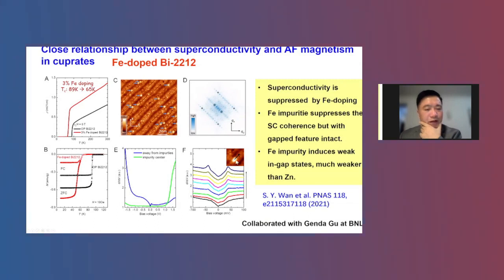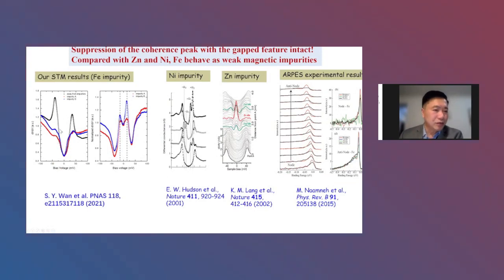But far away, you can see that it becomes a normal superconducting curve. Okay, so this is on the iron impurity doped BSCCO 2212. And here shows the contrast for the tunneling spectrum measured far away from the iron impurity, which shows a typical d-wave superconducting tunneling spectrum. But on the iron, you can see that the coherence peak is strongly suppressed, with the gap, however, intact, which again shows a strong local pairing.